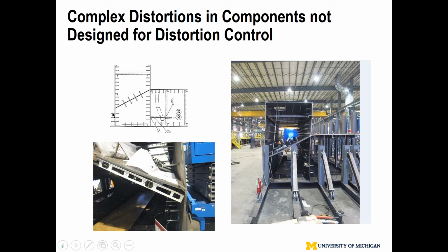What this says is, even after friction stir welding, you can still develop buckling distortion. That means there's no such thing as a low-stress, non-distortion technique. As far as the residual stress peak value is concerned, there's no difference. Theoretically, as I'm going to get into shortly, there's no difference between friction stir and arc welding, except the welding conditions are different because you impose quite a bit of fixturing. You go through all kinds of trouble to clamp it. But the clamping is okay as long as you are in the fixture. After taking it out of the fixture, on the right-hand side, you get this pretzel type of shape. That means there's instability, because this ring is inherently structurally unstable, and the only thing needed to trigger that instability is a shrinkage force as a result of residual stresses produced by friction stir welding.